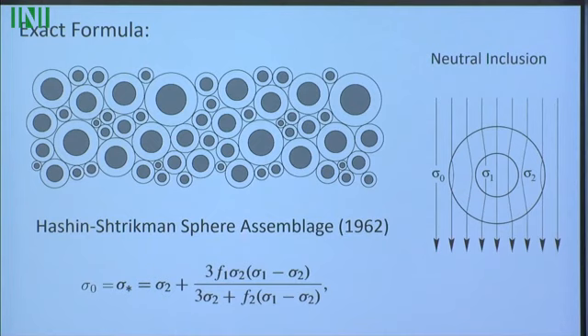And the key realization, this was Hashin and Strikman in 1962, although the idea is due to Hashin for elasticity in a slightly earlier paper. The idea is that if you've got a core of conductivity sigma 1, a shell of conductivity sigma 2, there exists an appropriate value for sigma naught where the current in the surrounding material is undisturbed. And so this is actually sort of an inclusion that's invisible to a uniform field.